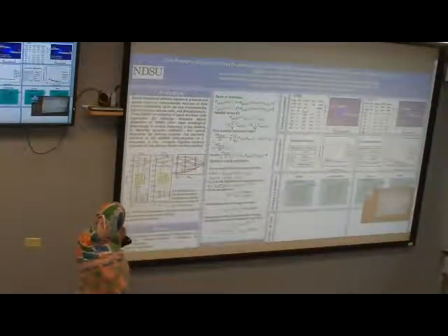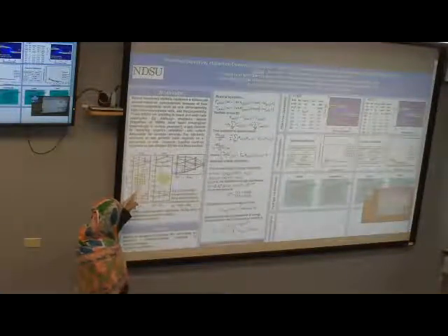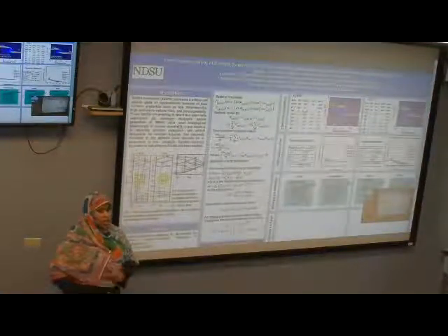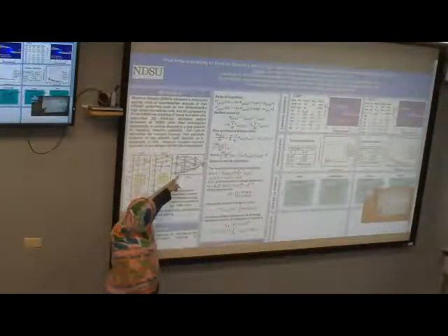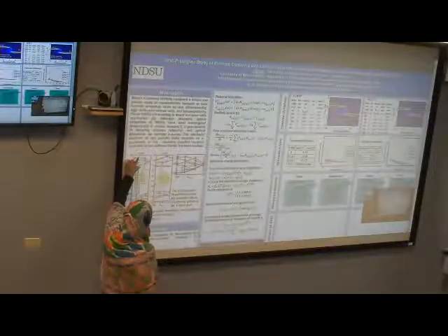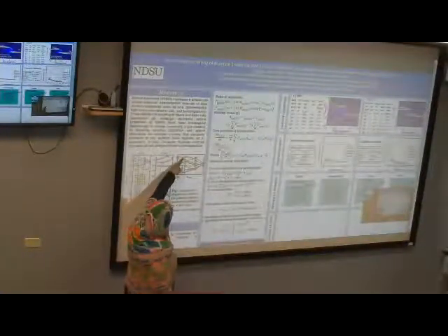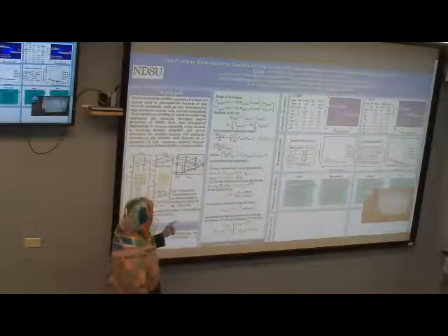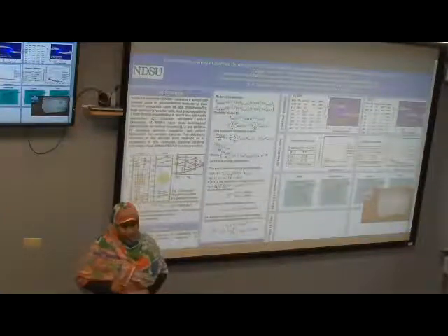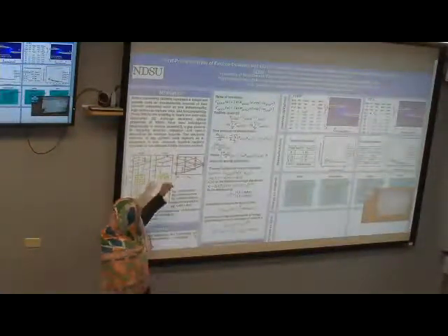Here we can see the models, a top view of the two nanowire models. And here we can see the transitions. This is a direct transition and this is an indirect transition, but this is for optical transition to excite the electron from the valence band to the conduction band. Here we can see a zoomed-in image of this portion, the conduction band of the silicon 100 nanowire. There are two kinds of transitions. One is at the same k point and another is from one k point to another k point. Same k point transitions are direct transitions, and transitions between two different k points are indirect transitions, and these are non-adiabatic transitions, by the way. So there are two optical transitions here and non-adiabatic ones over there.